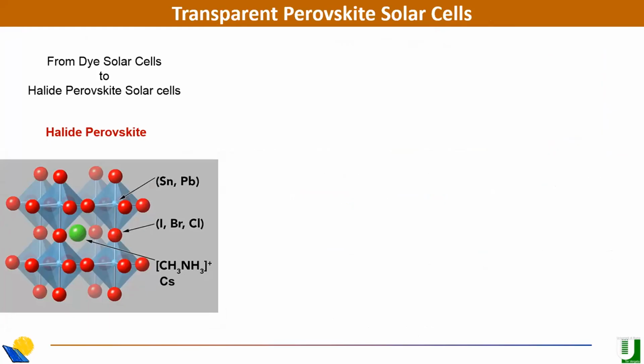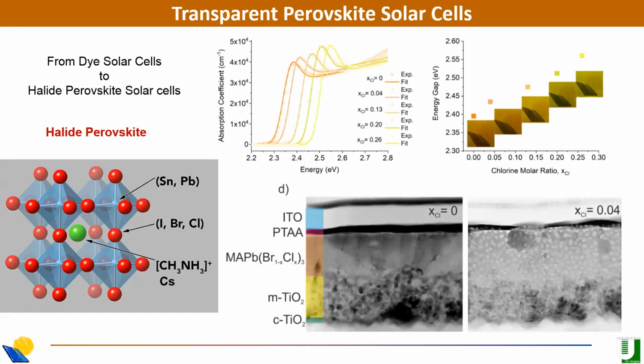The next step, actually, after the dye solar cell, was the introduction of perovskite, halide perovskite, and this was more or less motivated by the development made by the dye solar cell. Halide perovskite is a quite complex material, and you can change a lot of elements inside the crystal structure. One of the main elements is the lead, which is sometimes problematic because it's lead. But other elements, the halides or the other cations, can be changed to tune the properties of this material.